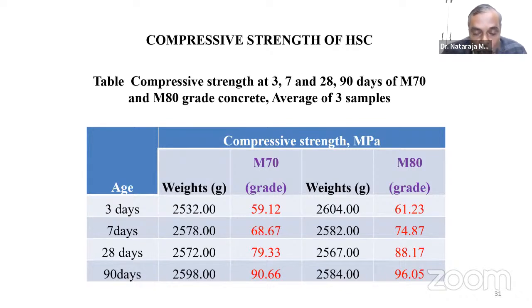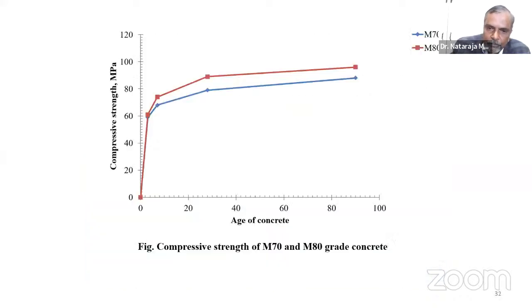Now, what is important is to cure the concrete for the first 7 days. And if you are not curing it for the first 3, 4, 5 days, and then later curing even for months together, you are not going to get the good strength. So this is one important point I would like to share with all of you. And the same thing, I have put it in a graphical manner.